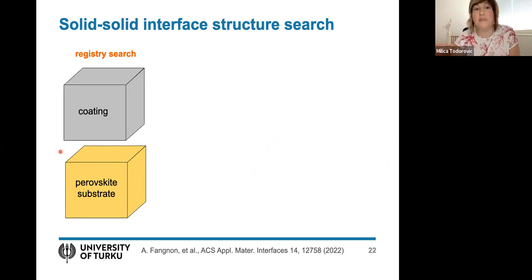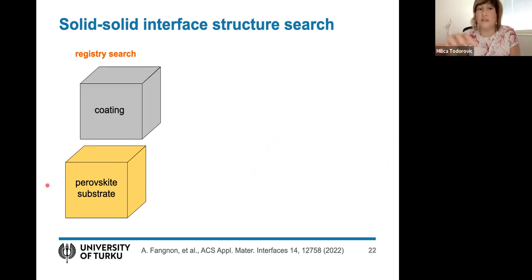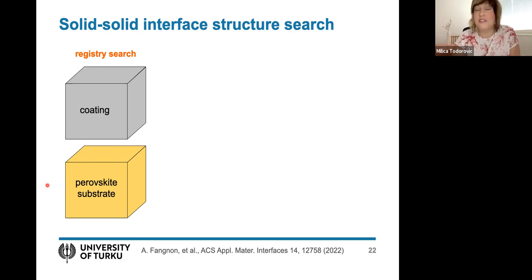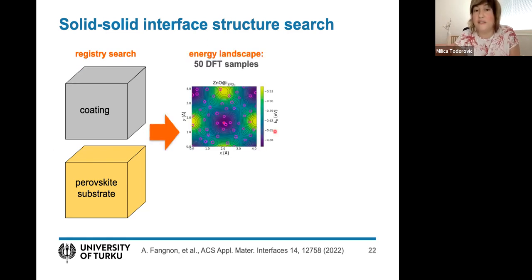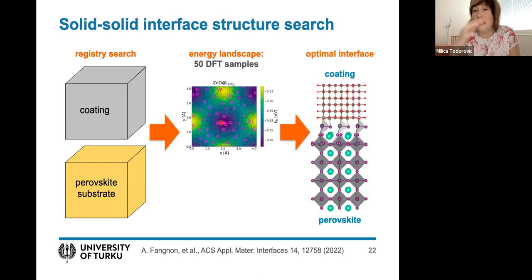So what we did is a simple registry search. We moved the coating around the surface in just X, Y, and then we found these kinds of energy landscapes for the binding energy between the coating and perovskite. And we quickly learned what was the global minimum location, and then we could put the coating on top of the perovskite and just relax everything and find the interface structure that forms between them.